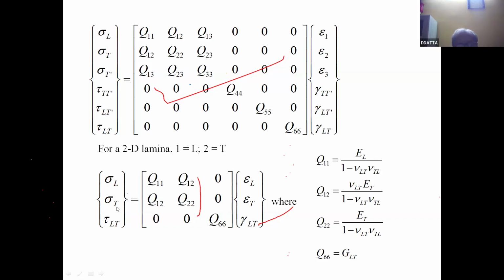That means there will be no shear strain because this is 0. Similarly, if I apply sigma T alone, there will be epsilon L due to Poisson's effect, due to this Q12, and due to this Q22, there will be a direct transverse strain, a normal strain. But as usual, there will be no shear strain because of this 0. Now, if I apply only shear stress, tau LT, there will be no normal strain, only shear strain because of this Q66.